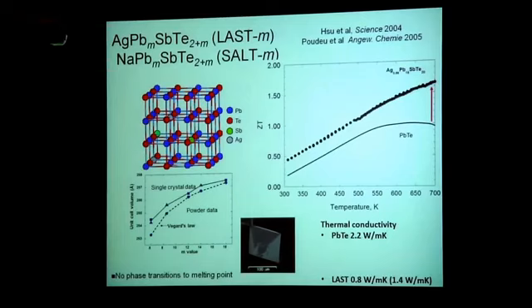This thing surprised us in that the lattice thermal conductivity was very low, about 0.8 watt per meter Kelvin. The parent compound, without any silver or antimony, was, as I said, 2.2. And based on theory, because you can predict the solid solution behavior, we could have expected about 1.4 to 1.5. Instead, we got 0.8. That was surprising. And this gave rise to a very big jump in ZT to record territory of about 1.5 for N-type material.